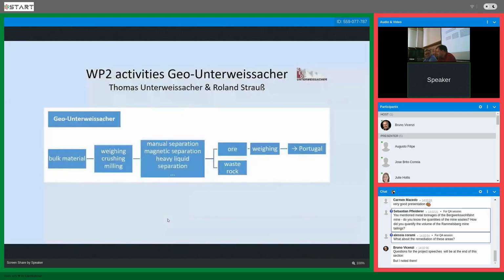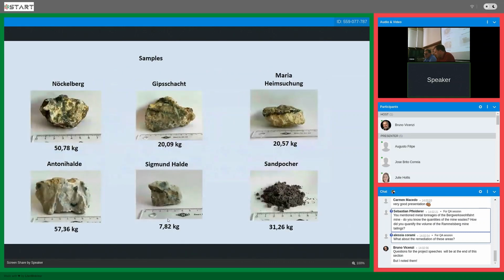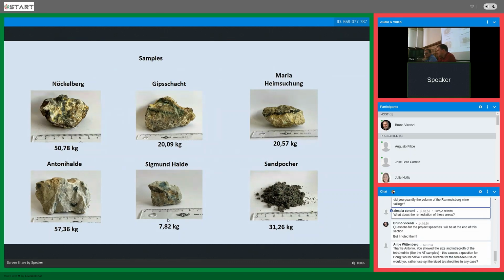Okay, thanks again, Piotr. Just a few words on the steps that have been performed during the project. So we collected the bulk material from the sites. After weighing, crushing, milling, we did some separation by sieving in the first instance, and we tried different approaches to separate the sulfides or to enrich the tetrahedrite in the first step. That was our approach, to produce a rich tetrahedrite concentrate, which in the end did not work out very well. But here you can see the different characteristics on one slide, how the input material looks. You have the lumpy ores from Nöckelberg, the different areas in the Nöckelberg area, and on the lower right-hand side we have the stuff which is sandy because it was crushed, mechanized. It was mechanized processing. So two different characteristics of those input samples.